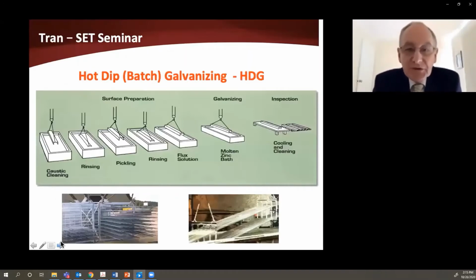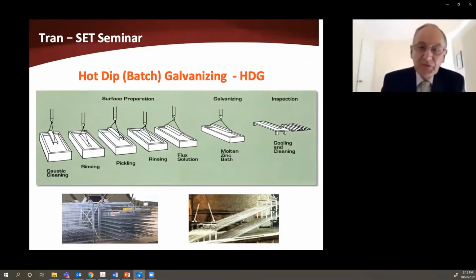Okay, so traditional batch galvanizing, there's a schematic of how this works. You're probably pretty well familiar with this, but the product moves through a series of baths: cleaning, rinsing, pickling, and pre-fluxing. And then this is the key part here, that the product is immersed in a bath of molten zinc for a period of time. Now, with reinforcing steel, these two photos down the bottom here show typically how straight lengths of bar are galvanized. They need to be put into cages or frames and then taken through the process. So this is very typical of commercial batch galvanizing.